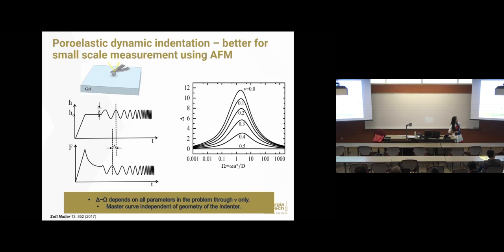And it's only different for different Poisson's ratios defined in poroelasticity. It's the drained Poisson's ratio, meaning you squeeze water out, wait until it reaches equilibrium, and see how much contraction you get in other directions. It's the so-called drained Poisson's ratio. It tells you how much water you can squeeze out of the network. And it's understandable that if you have a smaller Poisson's ratio, you can squeeze a lot of water out. So during this loading and unloading, you have more dissipation. So this phase lag value is bigger.